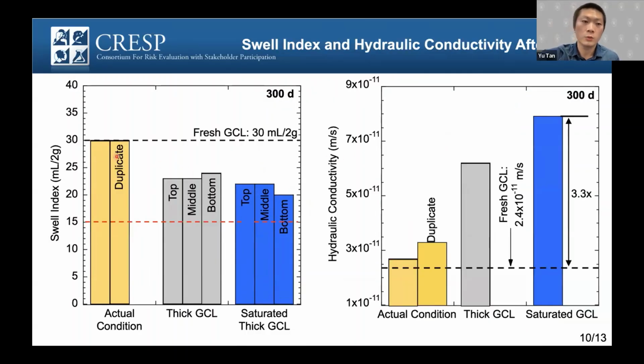And then we measured the swell index and hydraulic conductivity of the GCL after 300 days of interaction. For the actual conditions, where we tested the real GCL, the swell index is pretty close to the fresh GCL. For the thicker GCL, the swell index decreased a little bit. And for the saturated GCL, which is the worst case in our study, the swell index decreased a little bit more. And this result is consistent with our hydraulic conductivity test.